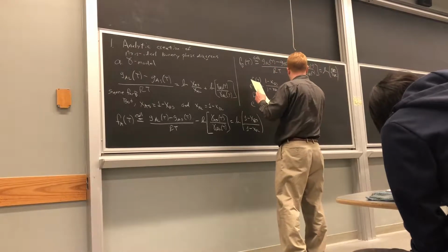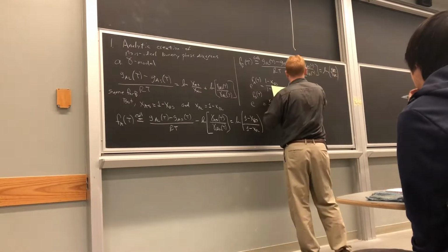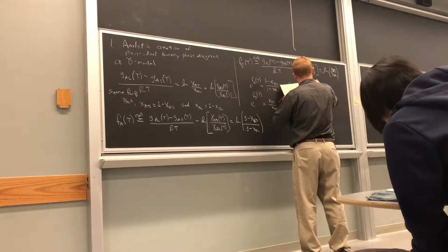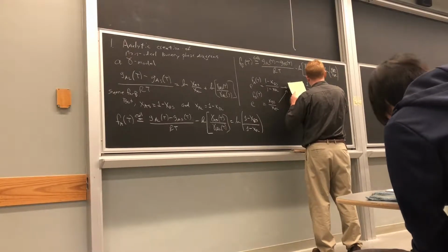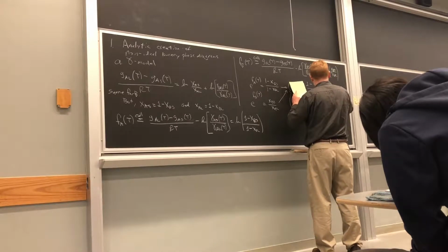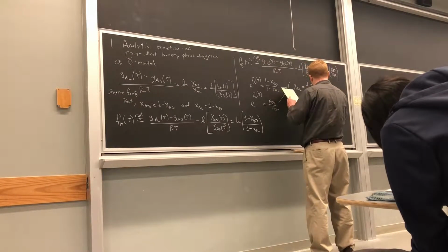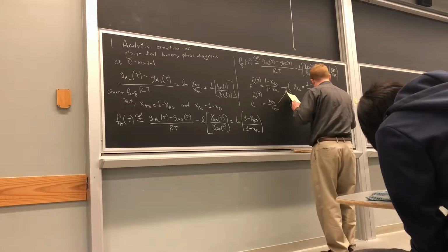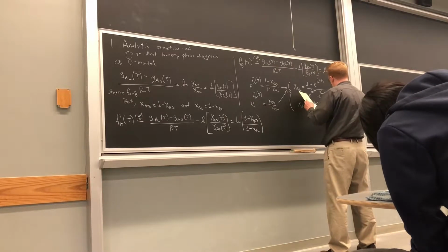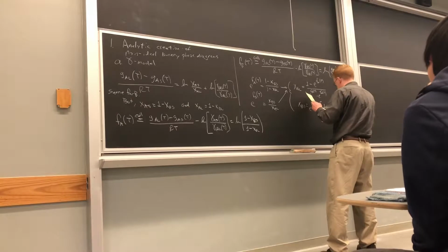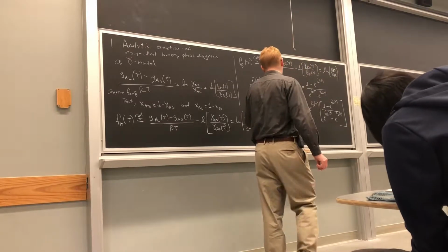And then when you combine these together, doing the algebra as we did before, you end up with X_BL equal to 1 minus e to the F_A of T divided by e to the F_B of T minus e to the F_A of T, and X_BS equal to e to the F_B of T times the bracket term, 1 minus e to the F_A of T divided by e to the F_B of T minus e to the F_A of T, which is quite similar to the alpha and beta equations that we had before.